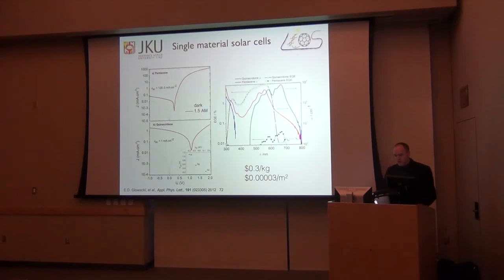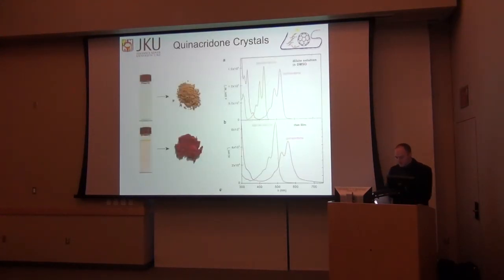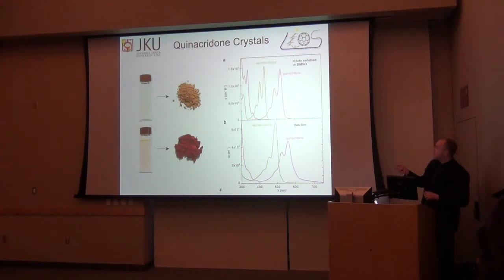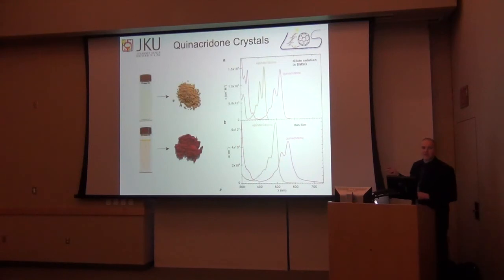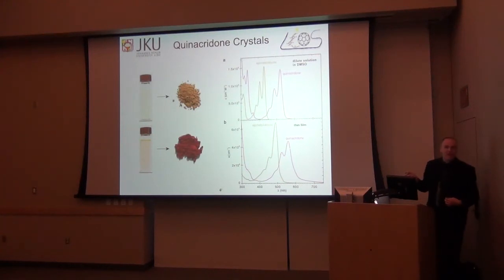So presumably if I cool this down, I could see excitonic emission, let's say, right? Yeah, and I didn't show the luminescence here, but in a typical molecular semiconductor, you'll have an absorption peak and some vibronic peaks, and the luminescence will look like a mirror of this absorption somewhere near the band edge. And in this quinacridone we see a little bit of the mirror signature, but you see a broad band emission into the infrared, which is kind of indicative of an excimer state, although it has not been well studied.